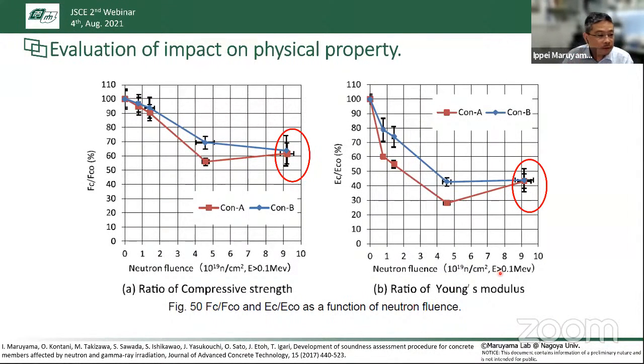So then, when we look at the strength change or Young's modulus change, these are the experimental results of the compressive strength and the Young's modulus of concrete after irradiation. The data are normalized per the properties of the sealed condition at the same age. As concrete is expanded, the properties deteriorated. In the case of compressive strength, more than 40% reduction was confirmed here. And in the case of Young's modulus, 70% reduction was confirmed here.